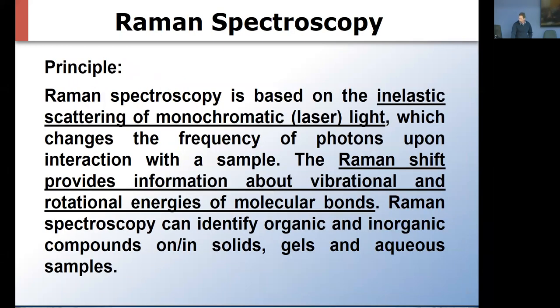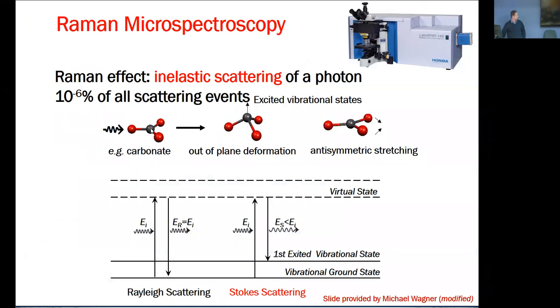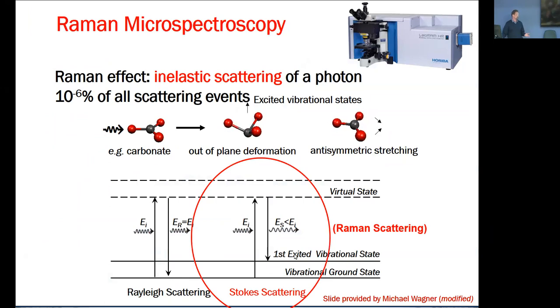Okay, so Raman spectroscopy is based on inelastic scattering of mostly monochromatic laser light. When this happens, the wavelength changes, and you basically record the spectrum of the emitted light. And this happens because vibrations occur in the bonds, and then the molecules go back into a non-excited or only partially excited state. So here's a carbonate ion, and if you shine laser light on it, you have a lot of elastic scattering or Rayleigh scattering, and about 1 in 100 million scattering events is inelastic, and that causes this Stokes scattering that we basically record as the Raman scattering.